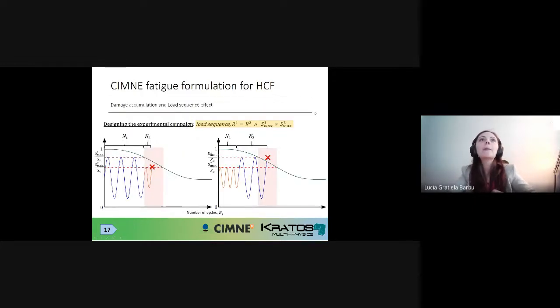Now an important thing for us, and this I didn't mention in the state of the art. Just let me say that when you are using the Miner rule, the linear damage accumulation rule, although it is very widely used because it's very easy to use and it's a useful tool for the industry, the Miner rule is not always correct. It has been invalidated for several different types of materials. Why? Because the Miner rule assumes that each cycle of loading has exactly the same degradation level, even if it's the first cycle of loading, even if it's the 100,000th cycle of loading. And this is not correct.